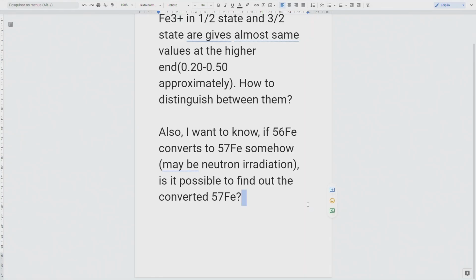One comment, only thinking about the question, which is very interesting. If the sample were made with only iron 56, and you irradiate it, in that case you will see only the converted one. But it's difficult maybe to have a pure iron 56 sample. So it's possible to switch.